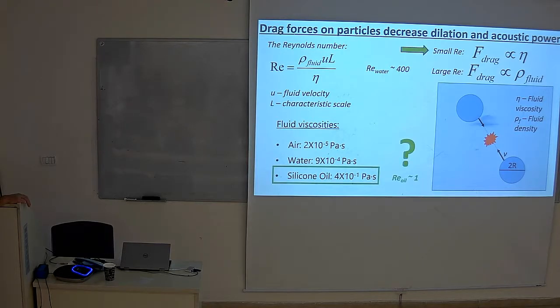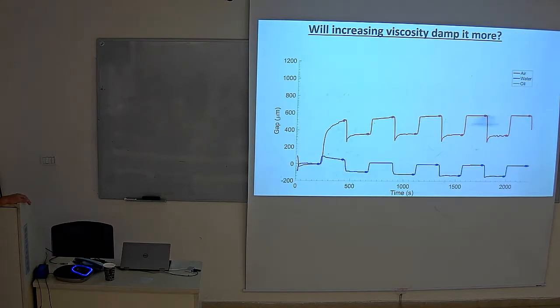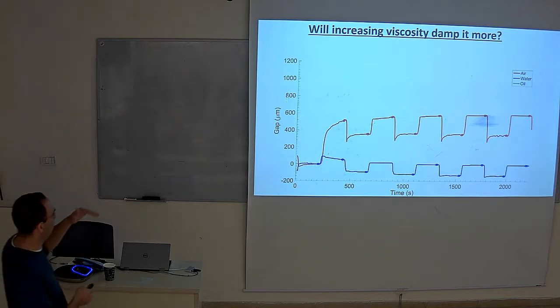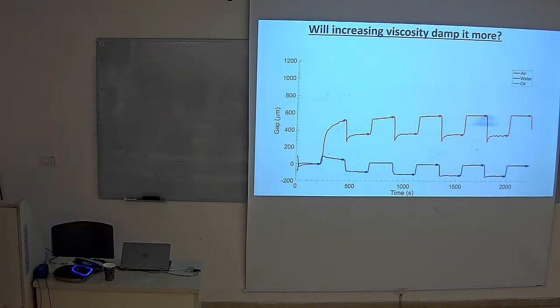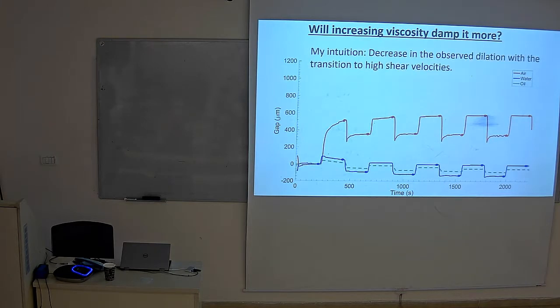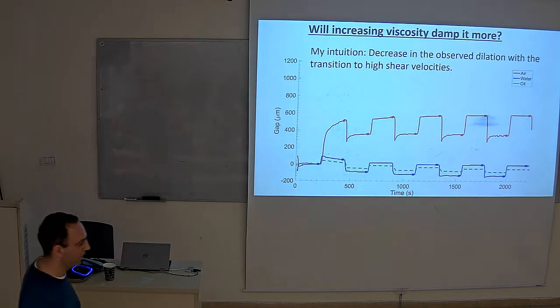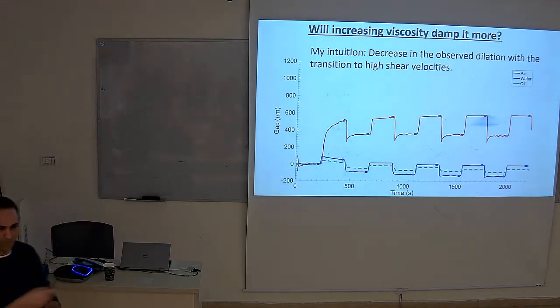So what will be the case if we use silicone oil, when we increase the viscosity and the density is more or less the same, there is not a big difference? Maybe we'll need to use a different equation for it. However, is it the same mechanism? So taking a different experiment, but the same idea as I showed before, gap, dilation, compaction versus time, with the same velocity steps: dry, water saturated, and what will be the oil case. So my guess, it will be something like that. We'll get something with even more damping because we have a viscous fluid.